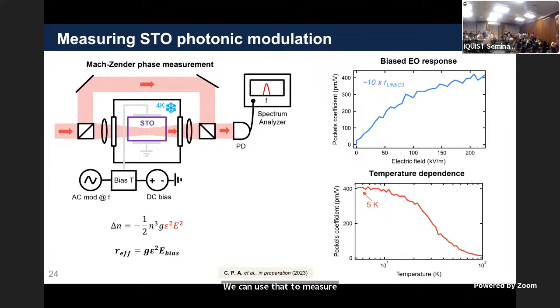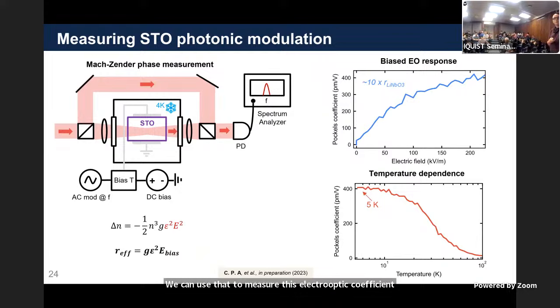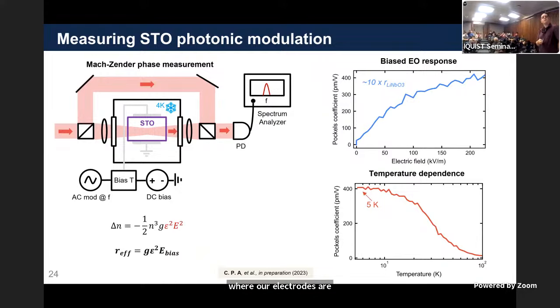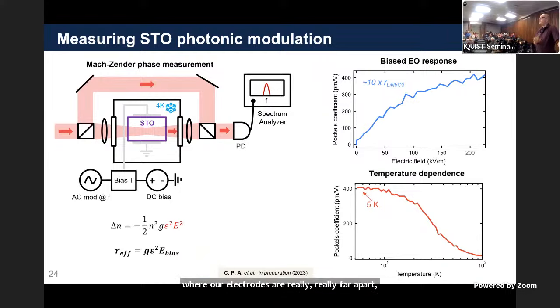And the exciting thing is even with a bulk crystal where our electrodes are really far apart and we're limited by our bias fields, we're already measuring nonlinearities that are 10 times greater than lithium niobate. And lithium niobate is this workhorse nonlinear optical material that's been used for these transduction dreams. So we're already beating the best available photonic material by a factor of 10 the first time we measured it at 4 Kelvin.